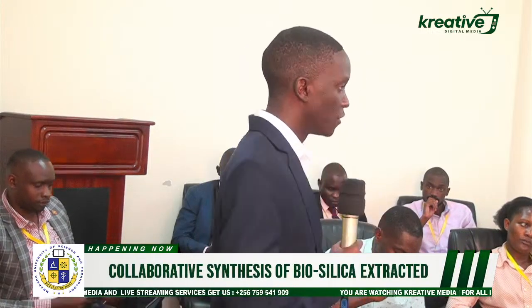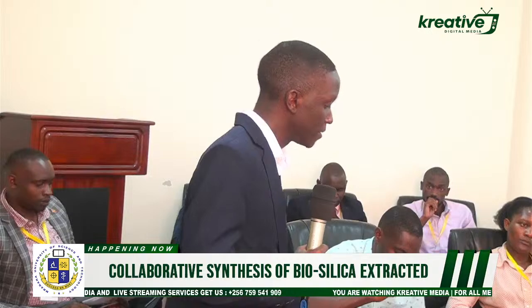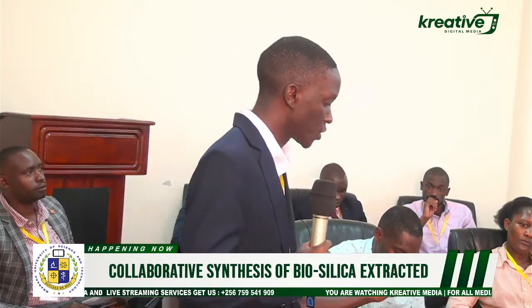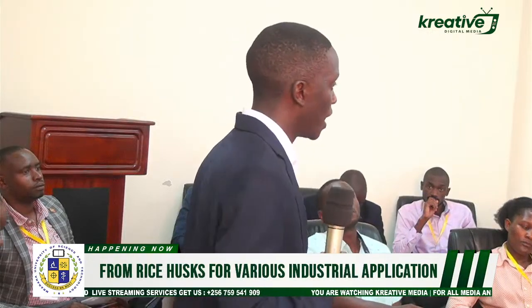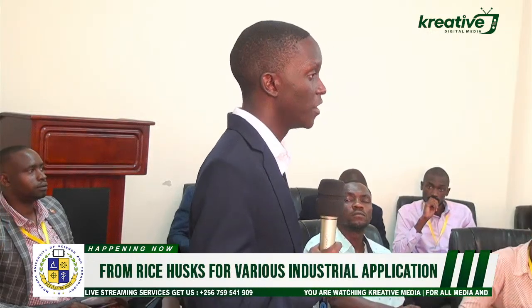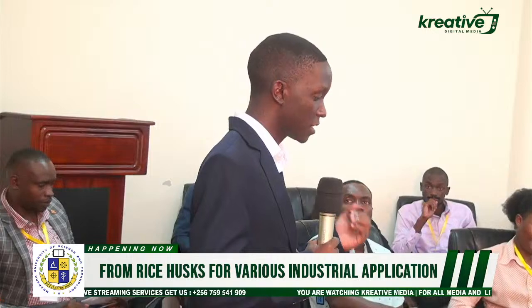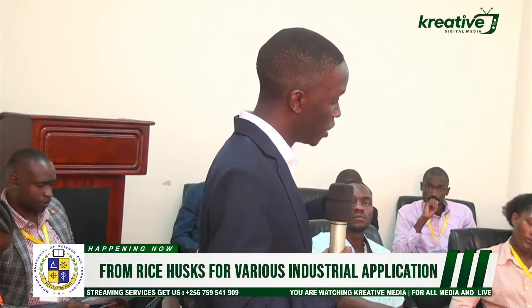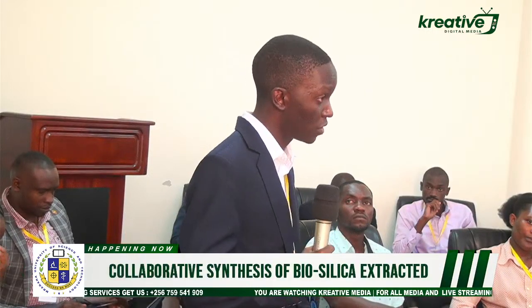So under my methods, for my specific objective one, the synthesizing, I'll have the rice husk collection. This will be cleaned and dried. Then I'll do the acid leaching to remove the minerals, to remove the metals from these rice husks. I'll wash with the distilled water and dry them. Then I'll extract silica by calcination at about 700 degrees Celsius. Then I'll dissolve this in sodium hydroxide to form sodium silicate.